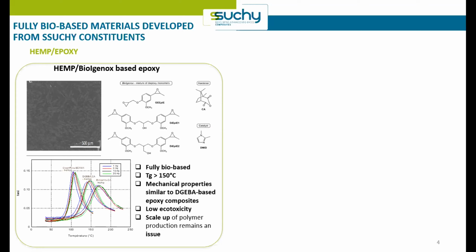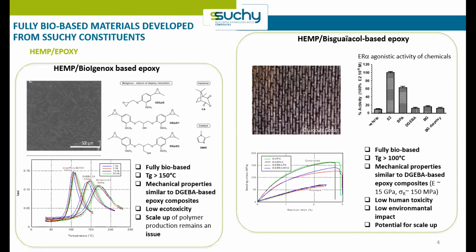And the problem that we are facing today is the scale-up of the production, because we need to find a company able to produce in large quantities the BioIgenox system. In parallel, on the next part of the slide, you can see the second composite, fully bio-based, 100% sushi materials made with woven hemp and the Bisguaïacol-based epoxy. So with this system, we obtained also a fully bio-based composite with a glass transition higher than 100 degrees. We obtained mechanical properties similar or even sometimes overpassing the ones obtained with the DGEBA-based epoxy system, with a low human toxicity. So as you can see on the top here on this graph, the estrogen activity was measured and compared to what we obtained with bisphenol A, as it was mentioned by Professor Christophe Thomas at the beginning of the session.